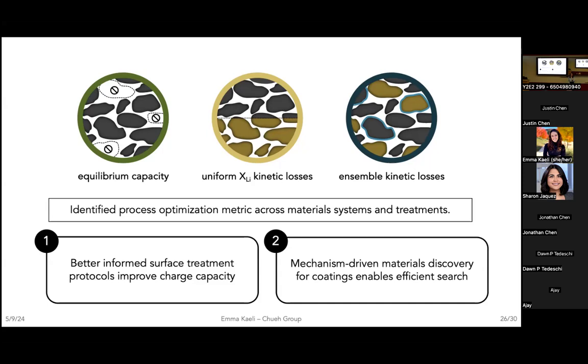The shape was a little different, but that has a lot to do with the mixed voltage interaction between the NMC particles and the solid electrolyte redox happening, because we don't return to the same exact lithiation state distribution among particles. Is that why you never went higher in time? I did go higher in time, and you don't get any more capacity. Okay, cool. That makes sense. Thanks.